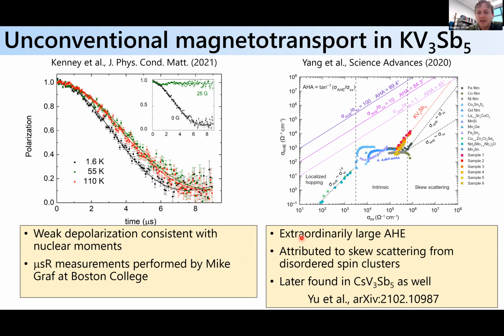What he was able to identify is that there was an extraordinarily large anomalous Hall effect that appeared in these materials. If you put it in this canonical plot of the anomalous Hall conductivity versus the longitudinal conductivity, it sits up here in this region that's typically ascribed to skew scattering. And you can see we're sitting in the regime that's above iron, for instance. So it's a very large anomalous Hall effect in this system.